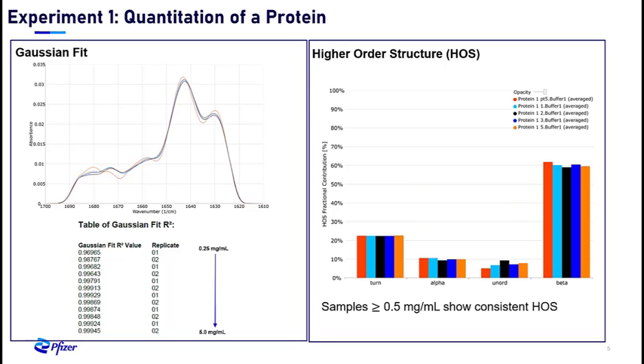In the last slide from this experiment, we show a Gaussian fit graph demonstrating how well the data fits. Also in this graph, we can observe the protein fingerprint of our sample. Here you'll observe on the x-axis the wave number or wavelengths with absorbance on the y-axis. At about 1642, we see a peak which is the signature for beta sheet secondary structure. To the right, at about 1630, we also see a small peak or shoulder. This wavelength is also a signature for beta sheet content.